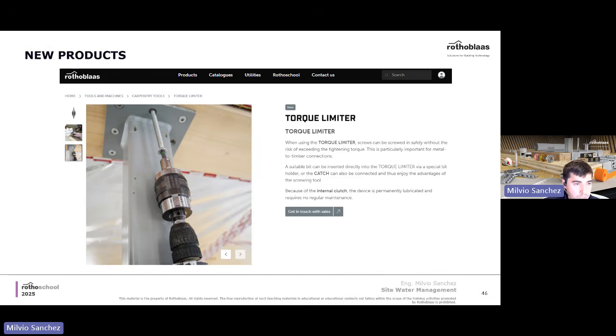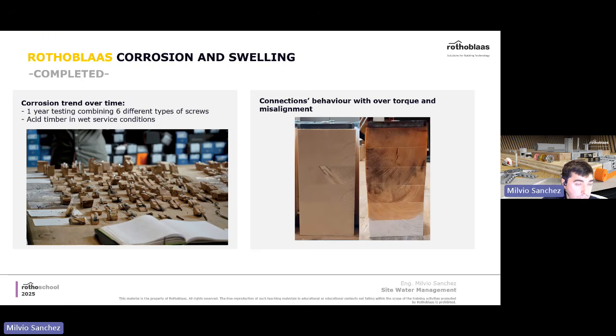You pretty much couple this mechanical tool on any screwdriver on the market, and as soon as you pre-select the torque that you want on the torque limiter, depending on the diameter and the length of the screw, as soon as it hits that torque, it's going to disengage, so the tool is not going to transfer more torque to the screw. So you can make sure that all of the connections are installed with the same torque, and it's a faster way than checking torque screw by screw. Because, as I said, this is relevant and can create some unintended tension forces.